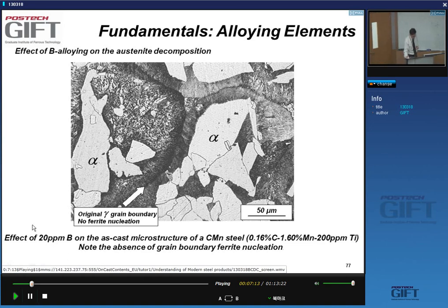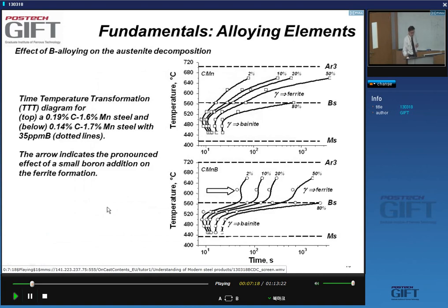Right, so this example was for 20 ppm of boron. And this is then what you see if you look at a TTT diagram. So remember, in a TTT diagram I do an isothermal transformation. So I do this test here. I go from this austenite range to this ferrite plus austenite range. If I do this without boron, in simple carbon manganese steels, 0.2 carbon, 1.6 manganese, I see